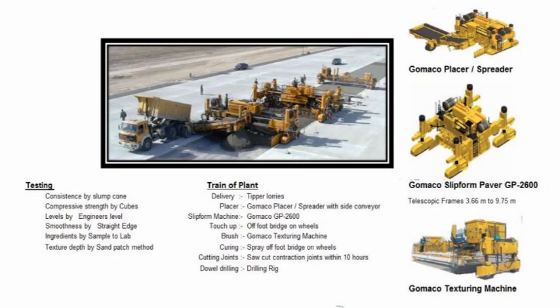Concrete airport slabs by slip form. The process consists of placing and spreading low slump concrete on the ground in front of a paver that slips over the concrete and extrudes the concrete as strips of slabs. Vibrators fixed along the front of the paver consolidate and fluidize the concrete. The concrete is then shaped by passing between the vertical side forms and underside of the horizontal profile pan as the paver moves forward.